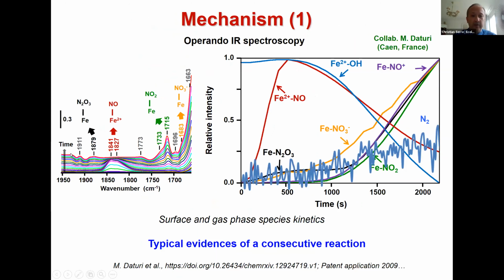What is the mechanism? So the mechanism is not complete, but you can follow the different species by operando spectroscopy, and you can follow the relative concentration as a function of time. You see that there's an evolution of the concentration, NO into the iron 2+ that increases, then decreases. Then you have formation of iron nitrite, and then NO2 and iron, and so on. And you can even see, it's noisy, an increase of concentration of nitrogen in the flux. So this is typical evidence of a catalytic consecutive reaction.